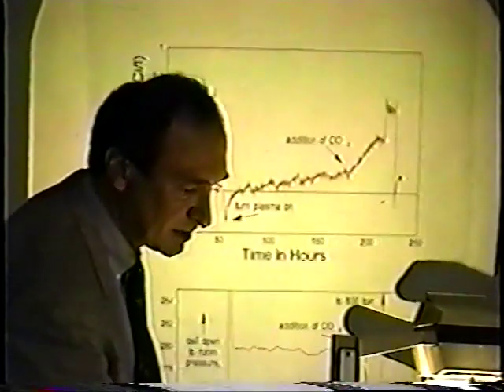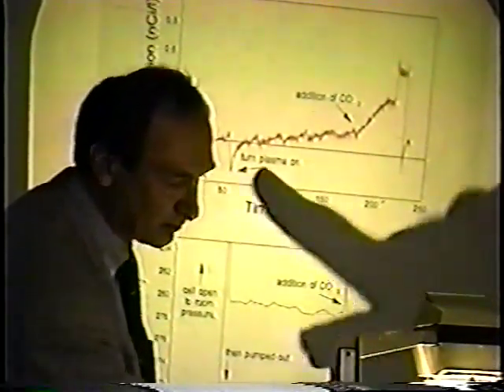And this is a typical result from palladium lithium. We've run a couple of these. There's just a small decrease in the output. So over 100 hours, you can see this one's just dropping down. And kind of compare that to the other one. You can see this one went up a little bit over 100 hours. Okay, so lithium doesn't seem to do anything for us. And after looking at like 50 or 60 of those, you get the idea that when it goes up, it's pretty unusual.